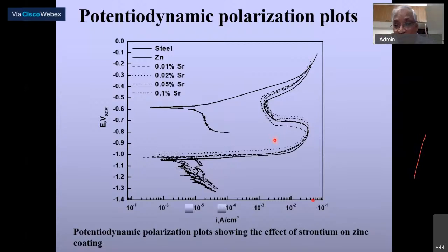So that means how we can interpret depends on whether you get an idea. Zinc cannot passivate in sodium chloride solution. If you have that idea, it automatically strikes you in front of your eyes that there's a problem. But nevertheless, I always tell people, when you do a polarization, please take it to the microscope. For heaven's sake, you don't lose anything. See them in the microscope. You get an idea about what is going on. Metallography and corrosion always have to go together. Okay.